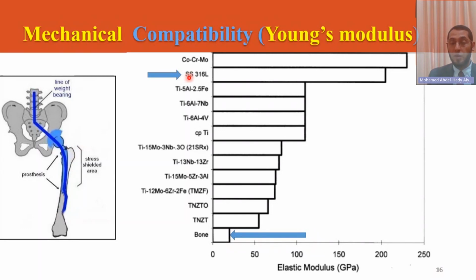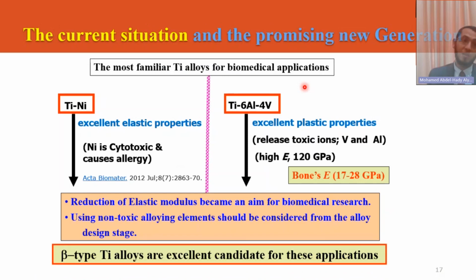So if we compare the commercial alloys already used in the market worldwide to the elastic modulus of the bone, you can see here the most common stainless steel, titanium 6-4, or cobalt chrome, and some other minor alloys used in the biomedical field. Compared to that of bone, you see the bone elastic modulus is very small, very highly elastic, but compared to all the commercial alloys, stress shielding is a big problem. For the last 20 years or more, there has been a big push to introduce new alloys with low Young's modulus to avoid stress shielding, which is one of the main reasons for the failure of implants or biomaterials after implantation.